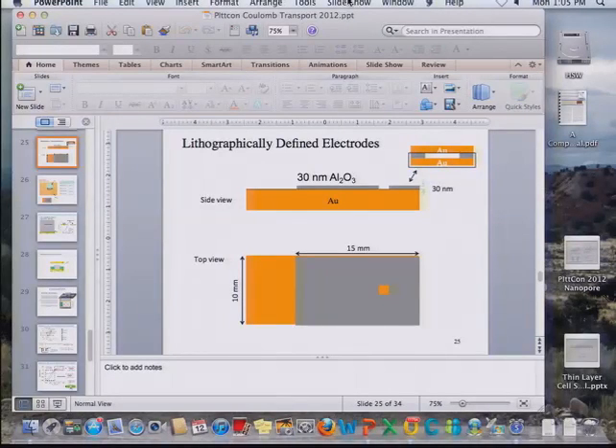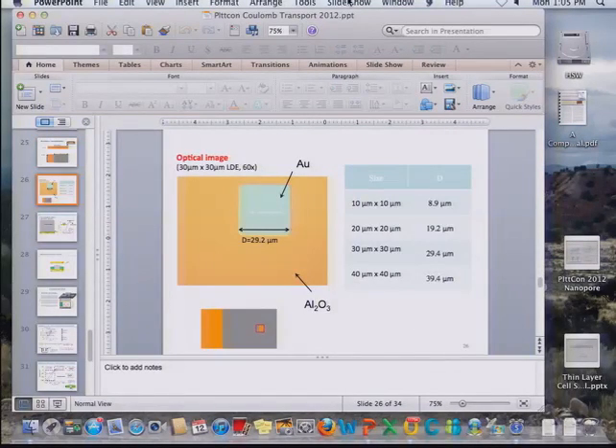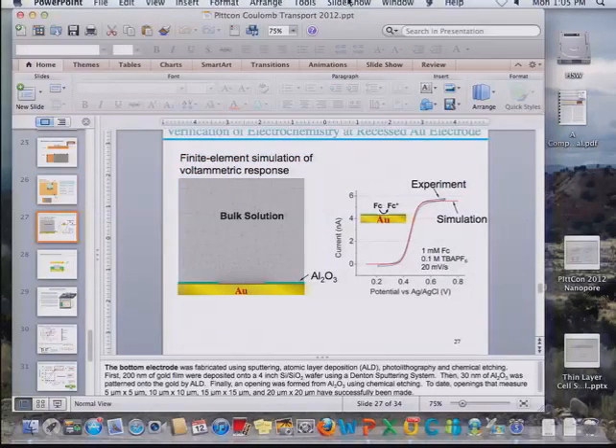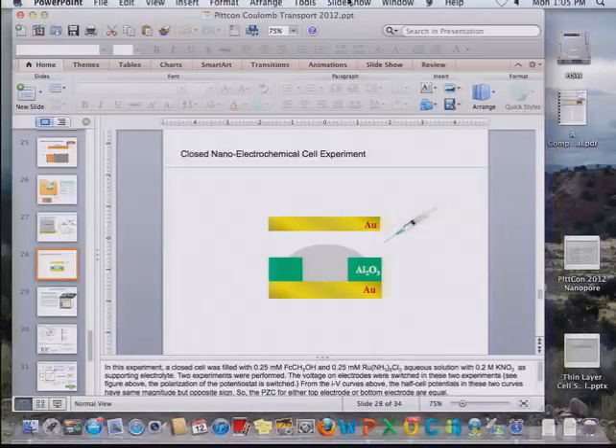And then the electrodes are lithographically defined. This is pretty straightforward stuff. So here's a gold electrode. Here's an optical image of the gold electrode. We make different sizes here. If you just take that electrode, this is shown in cross-section. Here's the gold, here's the aluminum oxide, and then there's a little region here that's exposed. And you do electrochemistry on it. It's very well behaved. This is the oxidation of ferrocene, and then there's a simulation on top of it, and it agrees perfectly. So these are nice, clean gold electrodes.